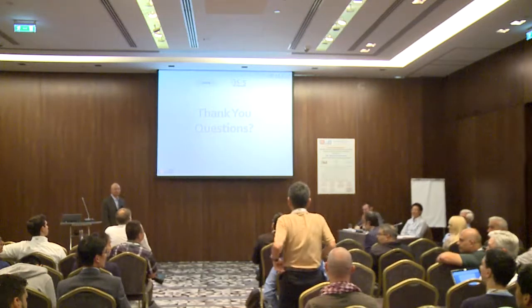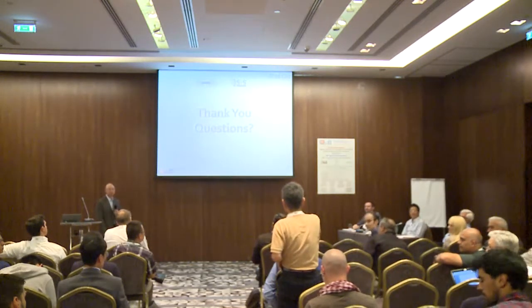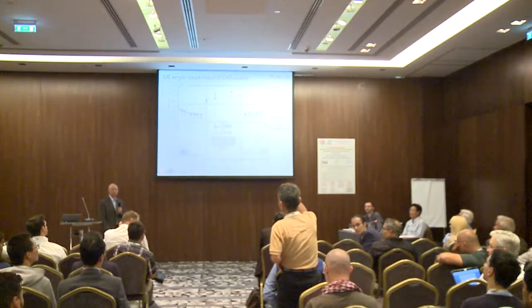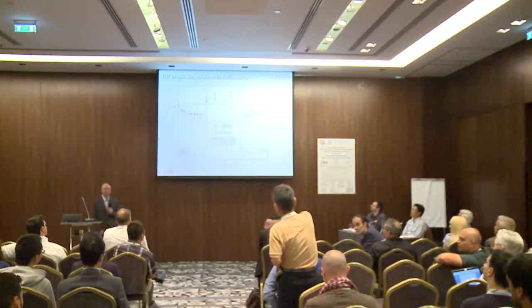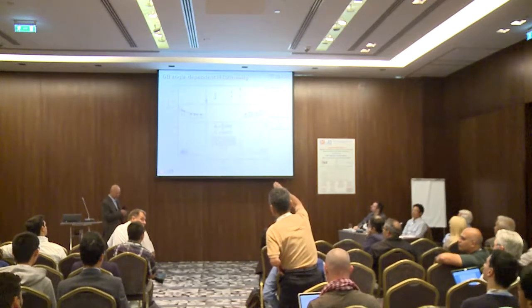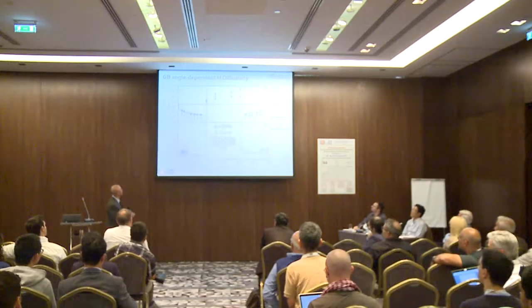You tried to explain the diffusivity from a low angle to a high angle. Right. Still we see the difference in the region of high angle boundary, at 30 and at 60 degrees, two orders of magnitude higher. So how did you explain that? That's a very good question. For this one, we don't have a predictive model for the diffusivity. What we did predict is a threshold. I think I have some backup slides.